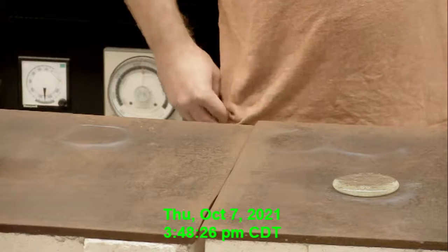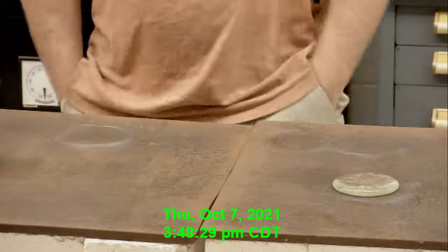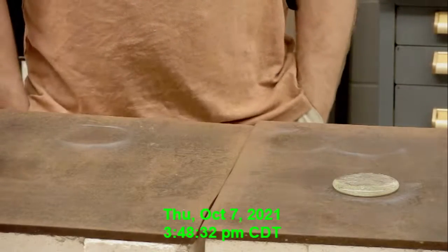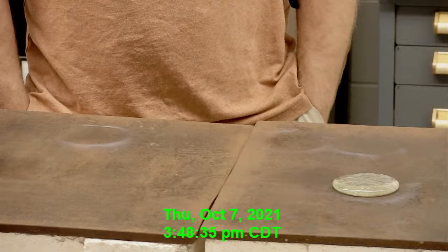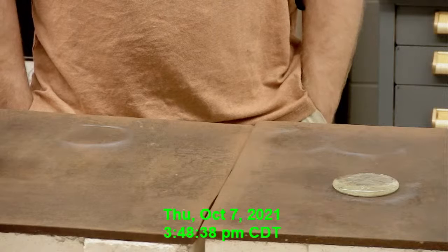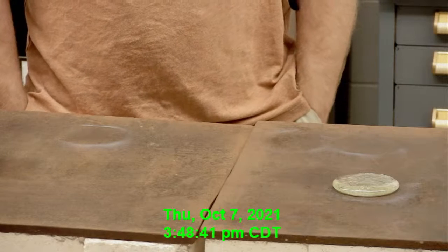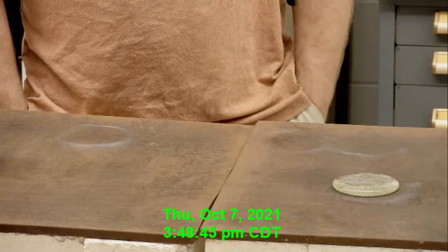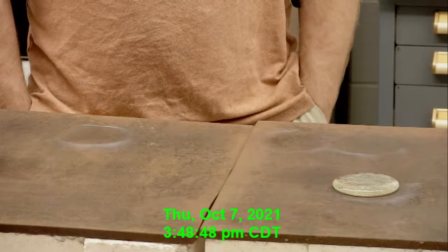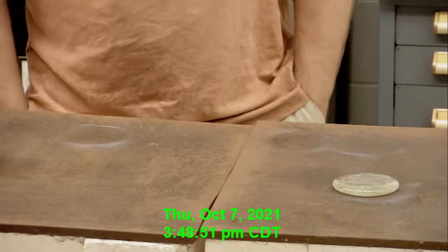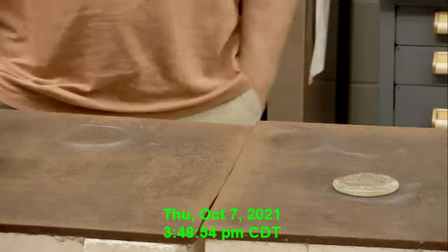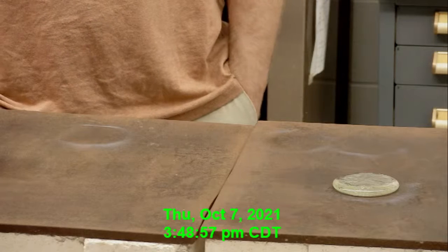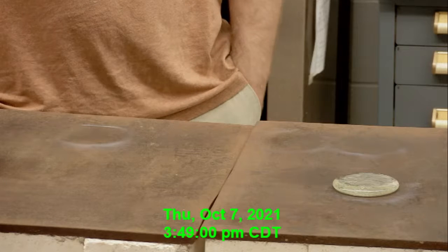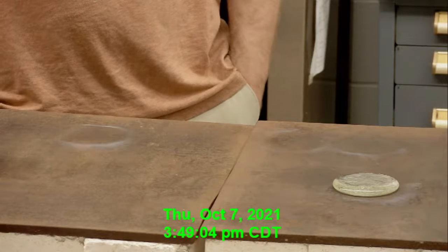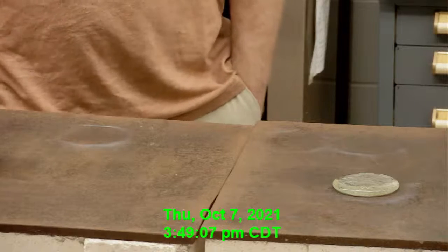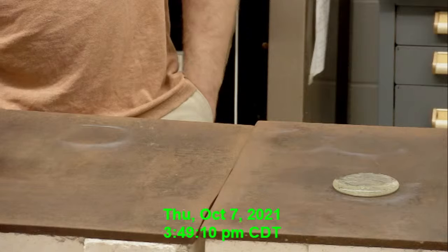As far as the color goes, the first time we tried it, I think we may have heated it longer, so it might have at one point had the right concentration to be brown, but no longer. So it just needs to get optimized, I guess. So we'll probably try increasing the loading. Some references say the iron is necessary too, and we may have had too pure, since we opted for the pure silica, pure ingredients. The bottle manufacturer may be assuming you're using a sand source that has a little bit of iron. So it could very well be there's not enough iron to see that color.